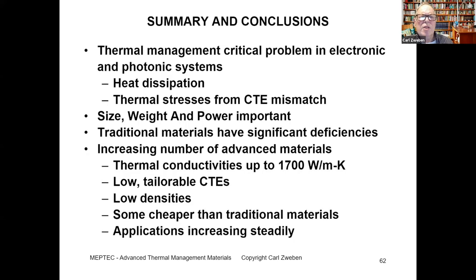So to summarize, thermal management is a critical problem in both electronic and photonic systems. It consists of heat dissipation and also thermal stresses arising from CTE mismatch. Size, weight, and power are critical issues in both commercial and consumer applications. We've seen that traditional thermal materials have significant deficiencies. In response to those deficiencies, we find an increasing number of advanced thermal materials with thermal conductivities as high as 1,700 watts per meter Kelvin in production.